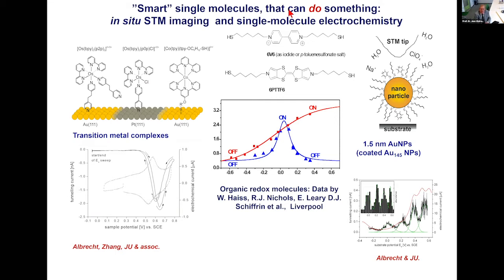Here are some examples. These are earlier examples, transition metal complexes. And you can see here the tunneling spectrum, and in the background, you have the cyclic voltammogram on the same molecule. Here are data from Richard Nichols and his people for two organic redox molecules. They show an interesting difference.